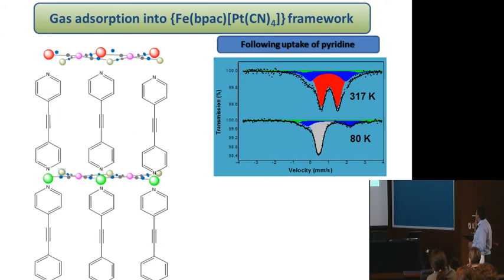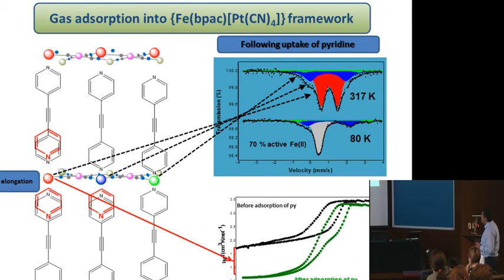Okay, again, we look at the Mossbauer spectroscopy for this compound, including the pyridine molecule. In this case, we can observe three different high-spin doublets, which can be explained as follows. The pyridine enters the structure and tends to decompress the system thanks to pi-pi stacking interaction between the BPAC and the pyridine, which is in agreement with the Mossbauer spectrum, with three different iron centers, depending on the vicinity of the iron and the number of pyridine entering the system. Okay?